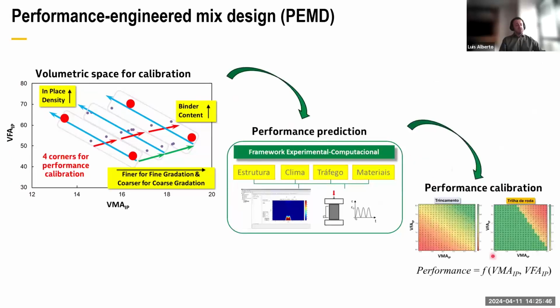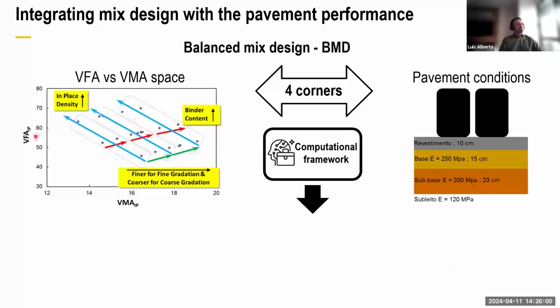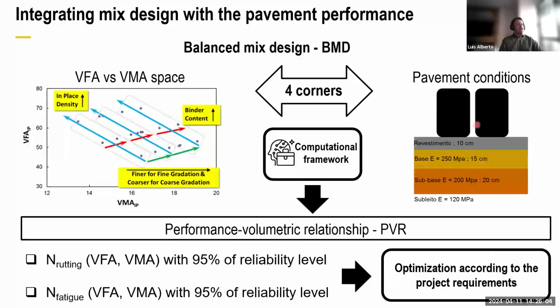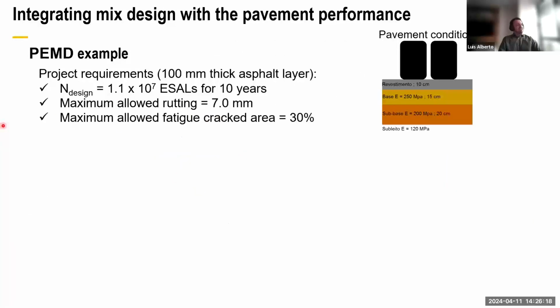The way we do this is based on the North Carolina State University protocol. We have a kind of volumetric space here. So we define some points for characterization. We call these the four corners. With these points, we predict the performance, and we calibrate the performance by using VMA and VFA. Once you have this performance calibration, we can optimize it and find the best point here to optimize the material's durability. This is an example here. So we have pavement conditions, the four corners, the volumetric space, and we have functions for rutting and for fatigue. So we can optimize it according to the practical requirements.